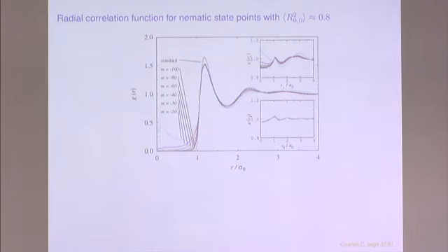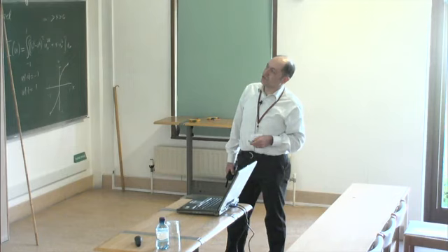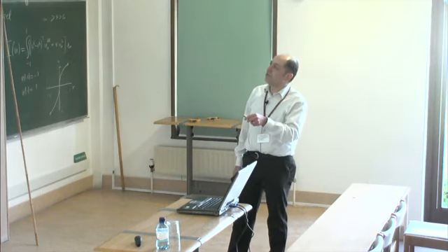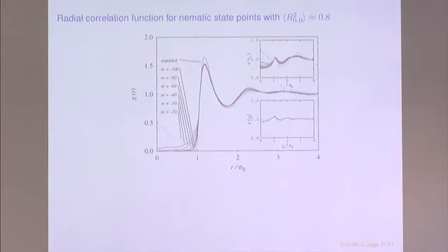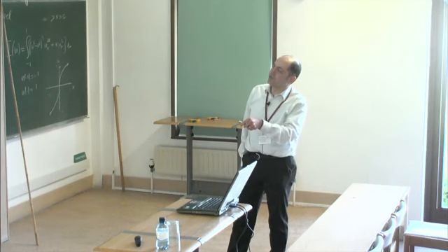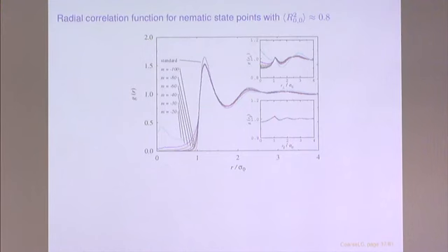Softness also affects the structural properties of these systems. The positions of the maxima of the radial correlation function are not greatly affected, only the height, but the places where there are larger changes are the distances corresponding to the strong overlap between the particles, and for the standard model the function here is practically zero because this histogram is practically not populated.